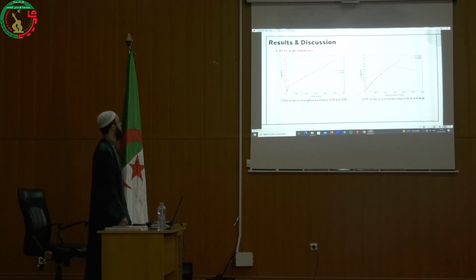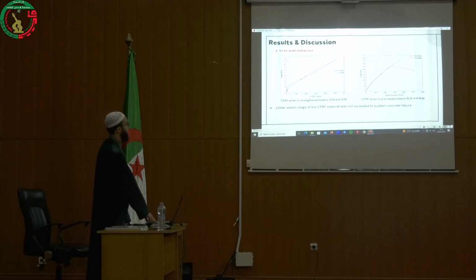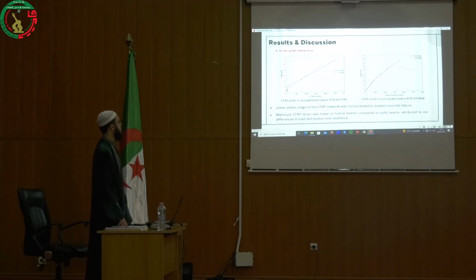Moving on to the load strain of CFRP materials. All the CFRP load strain curves of the tested beams show clearly that the linear stage of the CFRP materials was not exceeded until the sudden concrete failure. The maximum CFRP strain was lower in hollow beams compared to solid beams, attributed to the differences in load distribution and resistance.